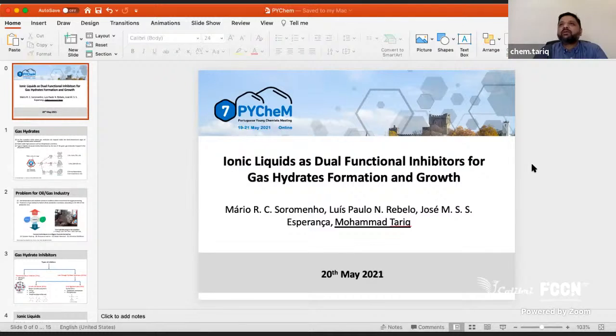It's very difficult. Right now, phenylalanine is a very known promoter basically, not inhibitor. But the problem is that hydrate formation is very stochastic in nature, so it's very difficult to predict. Thermodynamic inhibition you can predict, but formation is always a problem, because it's nucleation, and nucleation is very difficult to predict.